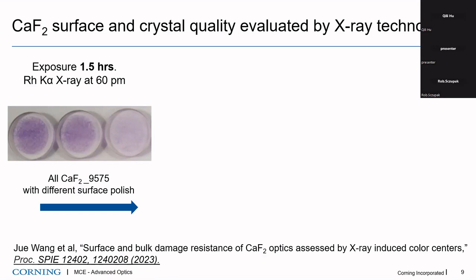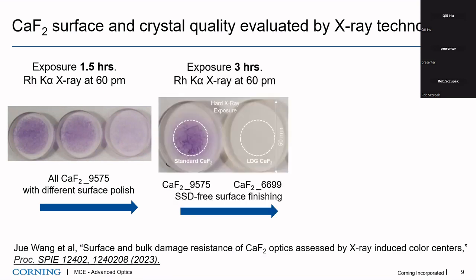With different surface polish quality, as you improve, you can see less coloration or defect formation under X-ray irradiation. And then we also developed laser durable grade calcium fluoride. So we use a similar technique and apply our so-called subsurface damage-free surface finishing.